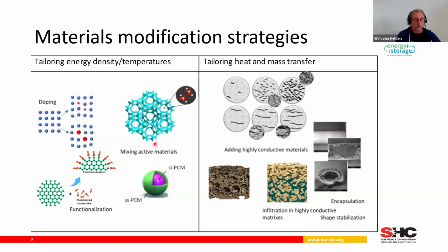Also, mixing active materials is possible. Here we have a lattice material of, for instance, a zeolite, in which a salt hydrate can be impregnated in order to make the salt hydrate more stable to prevent the fluidizing of the material. And last but not least, coating, encapsulating solid-liquid PCM with a solid-solid PCM, and therefore preventing the liquefaction of the first component.